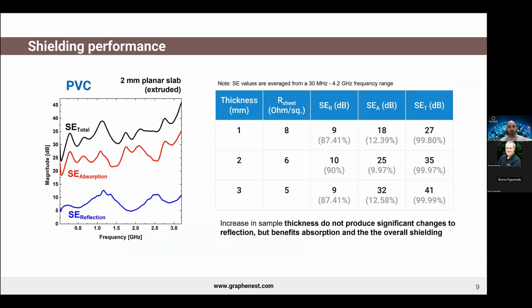So let's now explore G-Shield, starting with our PVC-based solution. On the left, we can observe the shielding spectrum. In this case, the magnitudes in decibels versus frequency from 30 megahertz up to 3 gigahertz. And this sample is a 2 millimeter planar slab, which was prepared by extrusion. So here at the plot, you can see the role of reflection and the role of absorption. But please don't be misguided by the impression that reflection is smaller than absorption. And I'm going to explain why in a few minutes.